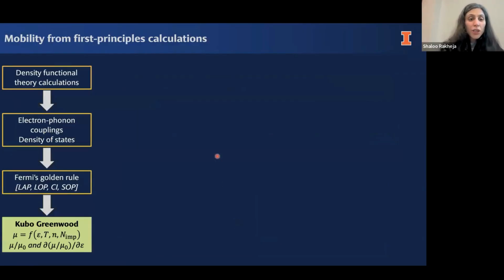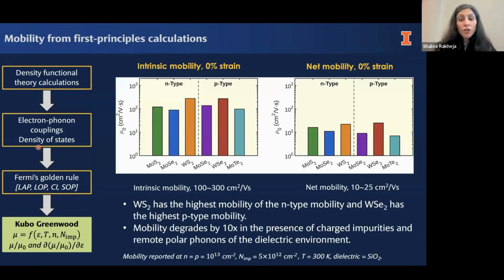We have a methodology, which I'm not going to get into. This took about a year to establish because these are very heavy-duty calculations. But suffice it to say, once we implement this correctly, we can predict mobility as a function of strain, as a function of temperature, as a function of impurities, as a function of electron densities. And from that, we can figure out what is the enhancement and what is the rate of enhancement. So let me show you some results over here.